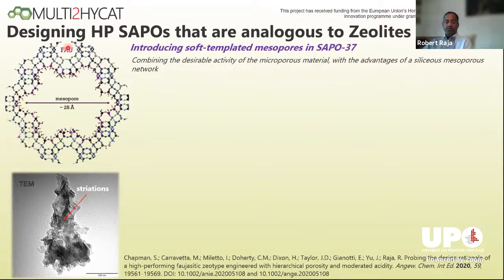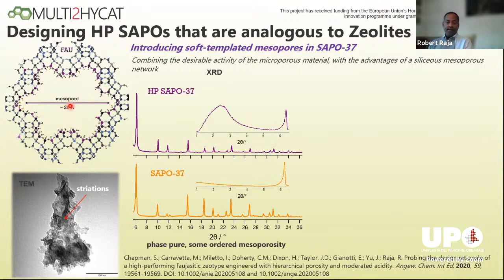This is a SAPO-37 structure, which is analogous to the zeolite faujasite. So this is zeolite X or zeolite Y, which has been used for the last 40 years in petrochemical refining. So this is a well-known, well-studied material. What we introduce now, through our soft templating strategy, is these mesopores. And one can use some standard techniques to look at, qualitatively, what the structure looks like. If you look at the X-ray diffraction, you see that the hierarchically porous structure has an X-ray diffraction pattern which is identical to the microporous structure, but then you see this broad peak at low angle, which gives you some indication that there is a hierarchical mesopore in the near vicinity.